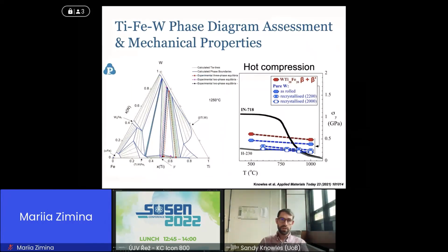So whilst we've done this experimental work to determine the phase diagram, we can take that then into a CALPHAD thermodynamic assessment. The ultimate aim is to try and do more prediction on these alloys, but if you don't have an understood phase diagram, you can't use many of the current predictive tools. But we're trying to develop that predictive capability. And we also then started looking at some mechanical behaviors. So in these ones, we're doing just hot compression, but up to 1,000 degrees Celsius. And in that, we're seeing massive benefits over state-of-the-art nickel-based superalloys or tungsten as a direct analog. So there is an advantage to having this tungsten material as well as having the beta-beta prime microstructure.